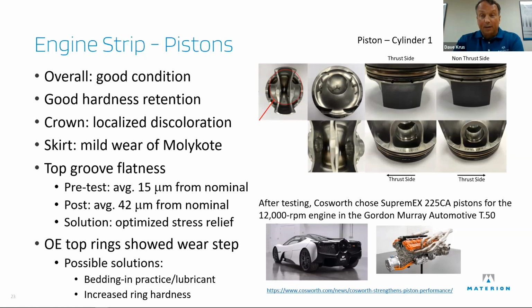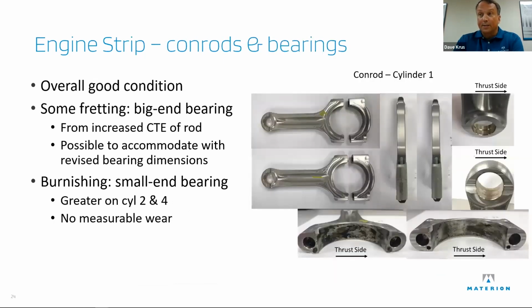The surprising thing, though, again, was the rods. The rods looked great. The rods were straight. The rods didn't wear. There was a little bit of fretting on the big end, and that's because the coefficient of thermal expansion of the aluminum metal matrix composite, the Supremex, is a bit larger than that of steel. And so it moved away from the big end bearing a little bit and allowed it to vibrate. We've talked to bearing manufacturers since, and a properly toleranced bearing would not have had that problem. So it's easy enough to solve.